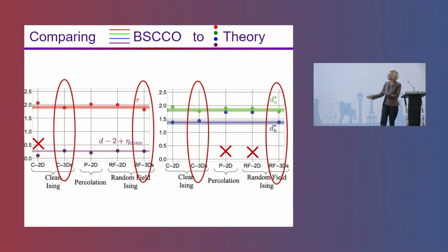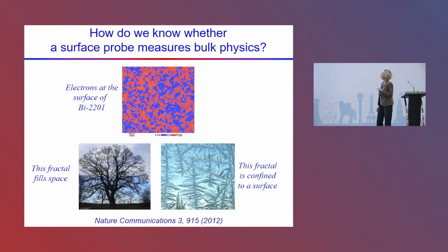So you can't tell from this. The numbers are too close to tell whether the disorder is mattering for the pattern formation. But I am excited that we can rule out the 2D models. That means the structures that they're seeing on the surface are coming from the bulk.